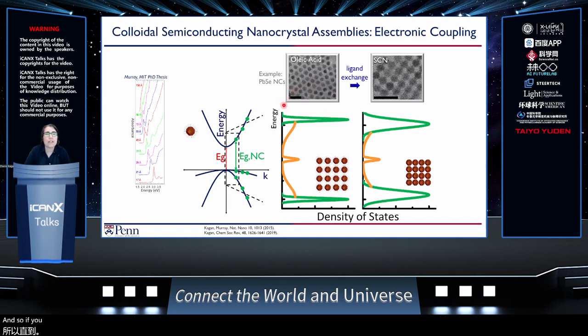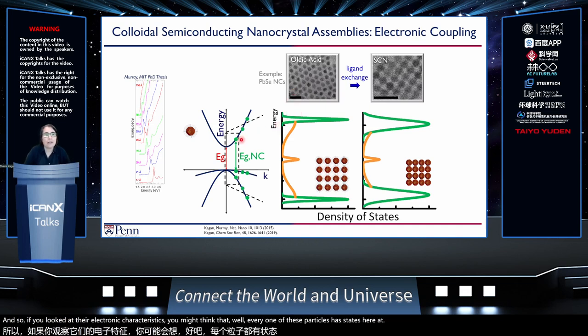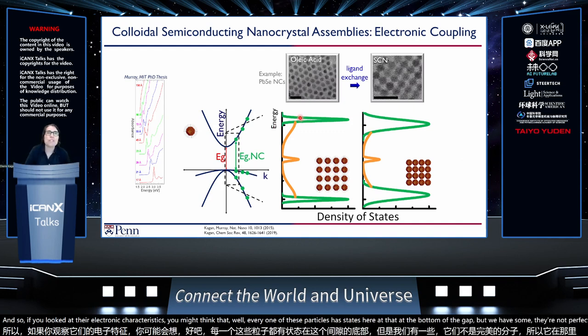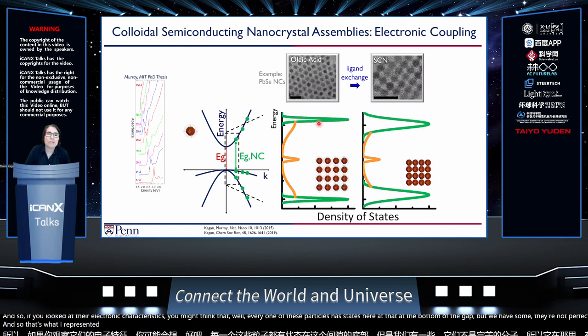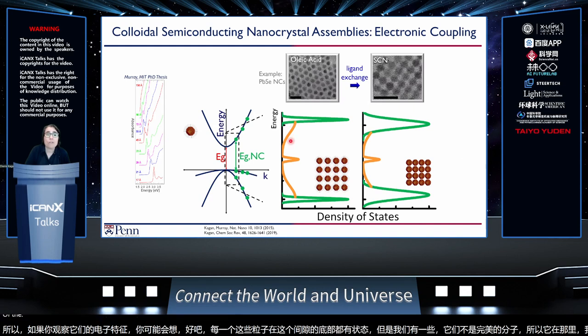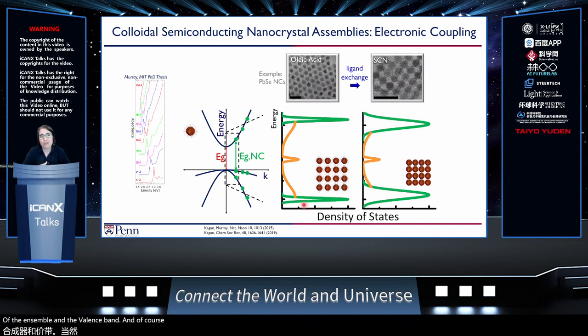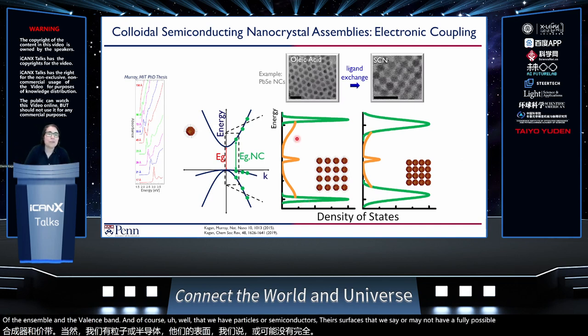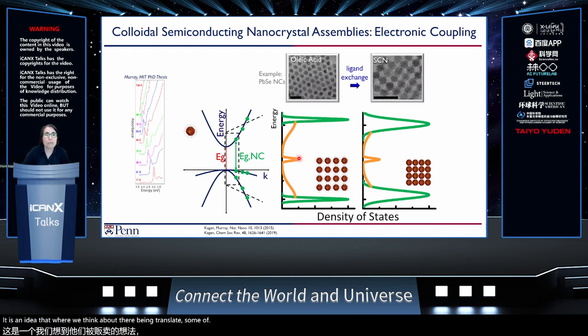And so if you looked at their electronic characteristics, you might think that every one of these particles has states here at the bottom of the gap, but they're not perfect molecules, so we have some inhomogeneous distribution. That's what I've represented here for the conduction band of the ensemble and the valence band. And of course, these particles are semiconductors, and there are surfaces that we may or may not have fully passivated. So what I show here in orange is the idea that there are trap states, some of them shallow, some of them deep, in the band gap of the semiconductor. I'll tell you a little about this as we think about transport in particular.